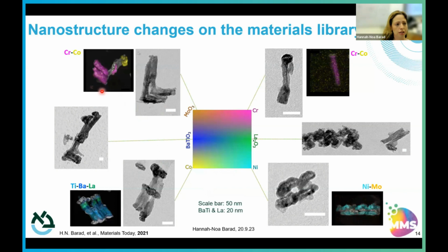So you can see that these L shapes are composed, the long side is composed of chromium, and then the top side is composed of cobalt. The edge parts of the zigzag are composed of actually nickel. The rest seems to be a lot of molybdenum. But of course, all of the different types of materials are here. Some like to very much interdiffuse between the layers. So the titanium, barium, and lanthanum interdiffuse heavily. But the nickel, for example, likes to cluster, as well as the cobalt.